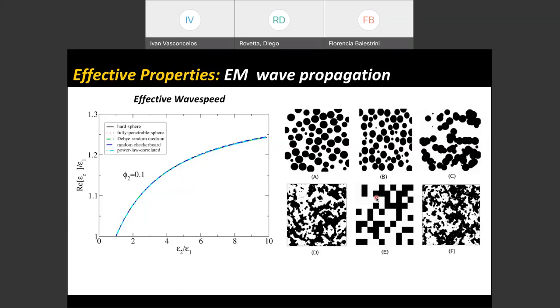Okay, so in this EM example, we have those six materials that we saw two-point correlations for before. And we see again realizations of the materials to remind you what these materials can look like. In all of these calculations, we have dielectric properties for the white phase and for the black phase. There is no conductivity, and the dielectric constant is purely real for both black and white phase. What this means is that if the material were only black or only white, there would be no attenuation. There's only wave propagation.